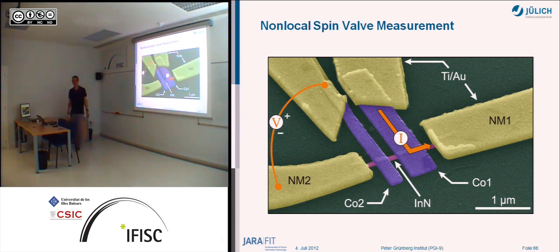Can you gate this structure? Yes, we can. Not here, to be honest. Here, in order to get a good spin injection, we had indium nitride, which was even doped. So it's almost metallic. So here, the gate control is really lousy. But in principle, one can do that using a back gate.